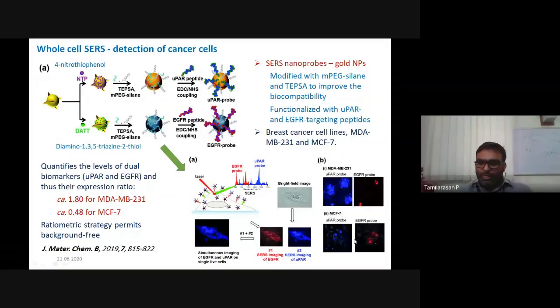But for MCF, in the picture it looks almost the same, but the EGFR probe is more intense here compared to UPAR, and they have made a ratio of these two, and they found that for MDA cell line, the UPAR to EGFR ratio is 1.8, and for the MCF cell line, the ratio is 0.48. So in the future, if you have any cell line, if you do Raman spectroscopy, and if you find that the UPAR is more in that cell line, then you can simply tell that it is an MDA cell line. And if the EGFR is more, then you can tell that it is MCF cell line.